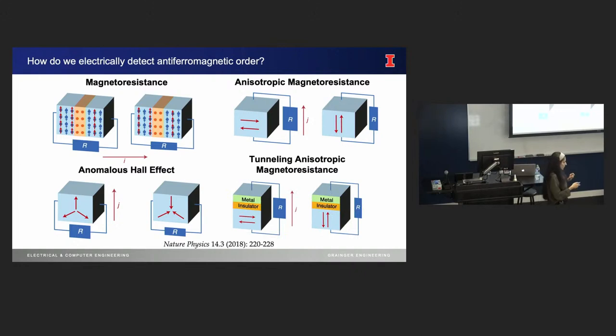And finally, we have this thing called tunneling anisotropic magnetoresistance, same as the top one, anisotropic magnetoresistance. It's just that the structure is a little bit complicated. The effect is a little bit stronger than anisotropic magnetoresistance, but typically this last one does not persist to room temperature. There are some challenges. I know that people have been trying to do that in materials like IrMn and so on.